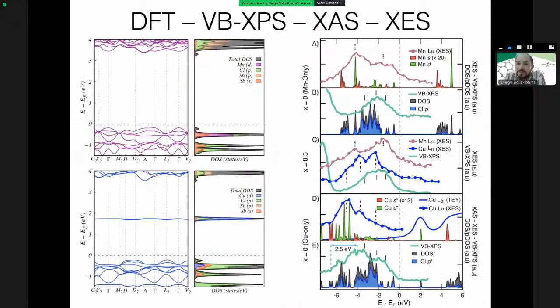And what we did then was we wanted to understand these materials and their electronic structure. So we relied on DFT calculations, and we validated those calculations with extensive studies with XPS, X-ray absorption, and X-ray emission, which told us that we really had done a good job modeling these materials and that we really understand how to model these materials.